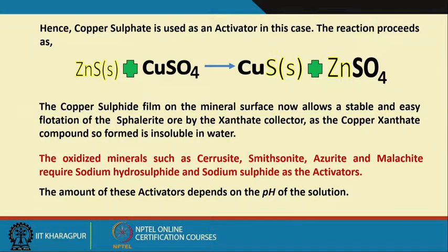That means the ZnS surface is getting coated with a CuS, and that helps you in the flotation process, that is by making a copper xanthate. That means the original material surface you have changed, so that its affinity towards your collector is much more.